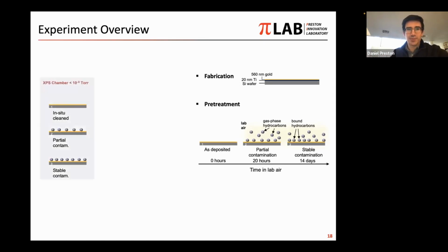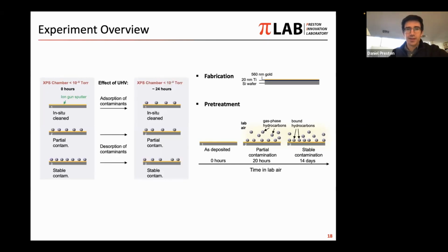So we take these 3 types of samples, put them in the chamber, just to make sure that our clean sample is in fact fully clean. We do an ion gun sputter inside the chamber, and then we see what happens over time. And what we observed, summarized here schematically, and we'll go into more detail in a moment, is that the clean sample adsorbed contaminants even inside the ultra-high vacuum environment. And the samples that were contaminated actually desorbed contaminants. And so you might have a sample that you just pick up from the bench in lab, put it in the XPS, try to quantify it. You'll find that, in fact, the composition of that surface is changing over time as a result of sitting in the ultra-high vacuum environment, and you may get inconsistent results there too.